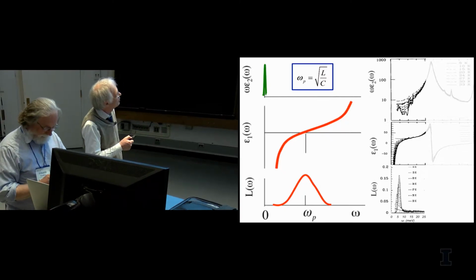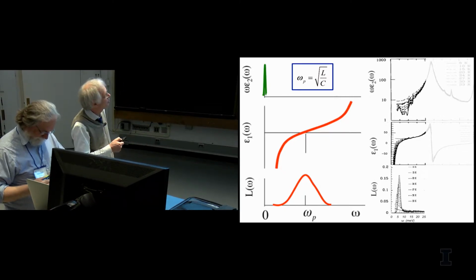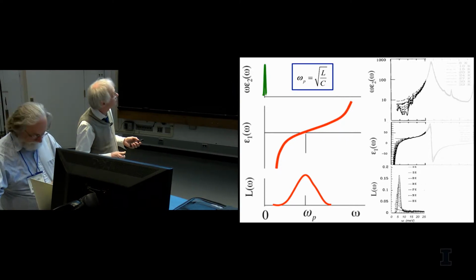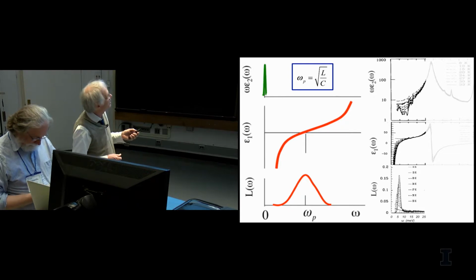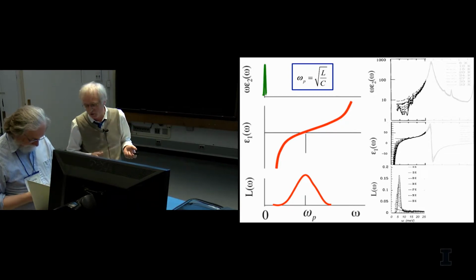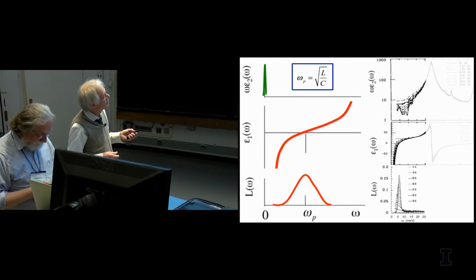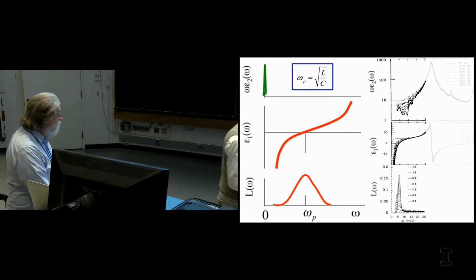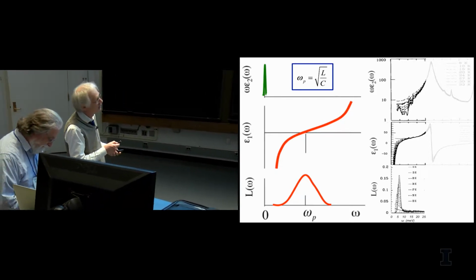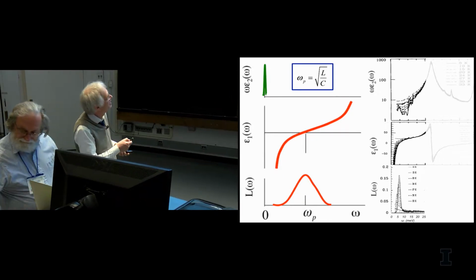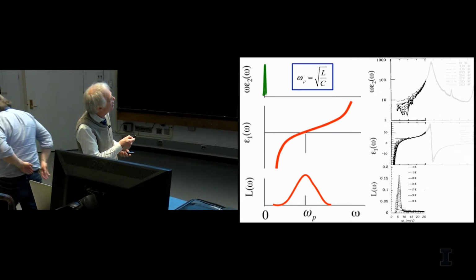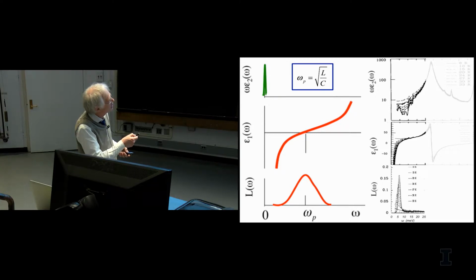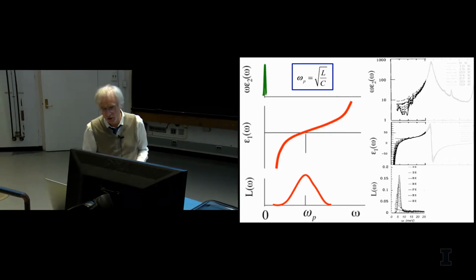What's plotted here is one of these cuprates, it doesn't matter which one, it's lanthanum strontium copper oxide. What you do not see here is this delta function, because you do not measure zero frequency, you only get finite frequency. Okay, I got another pointer now, but this is fine. What you have here is the opening of a gap in the optical conductivity. There is a phonon which is not important, that's why I made it somewhat grayish. And here you have this zero crossing of the dielectric function. Where it crosses zero, you get a peak in the loss function. This is your plasmon, and there's a delta function in the optical conductivity there. Those are the two poles you have.